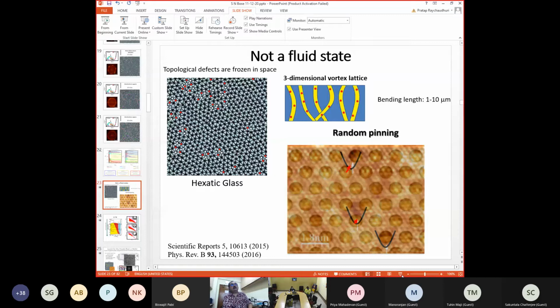Pinning means we have defects. This is a high resolution, atomic resolution image taken on a tiny portion of this crystal using the same STM. Here you see selenium atoms, but you also see some points which are darker. These darker points we later figured out are actually cobalt impurities in niobium diselenide. These cobalt impurities act as potential wells for the vortices. This is a cartoon of a vortex lattice, not a real vortex lattice. These vortices will try to get displaced from their equilibrium position in this lattice and go to the potential well position. So this distortion is actually producing the hexatic glass state.